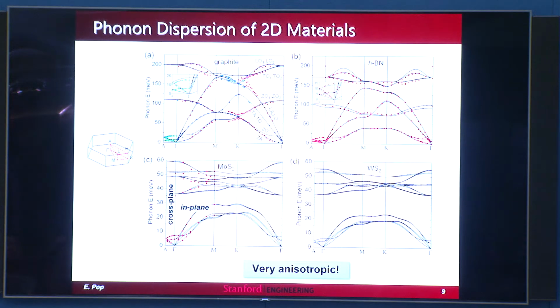If I'm going to show you the electron dispersion, I probably should show you the phonon dispersion of these materials as well. It's a bit of a messy plot. It's for multiple materials, but I think the take-home message here is that it's a very anisotropic phonon dispersion. And this has to do with the in-plane covalent bonds versus the out-of-plane van der Waals bonds.